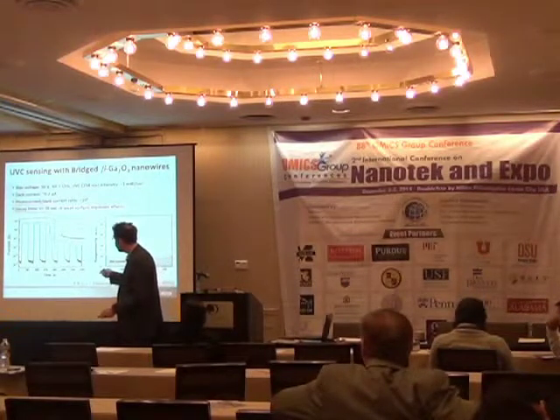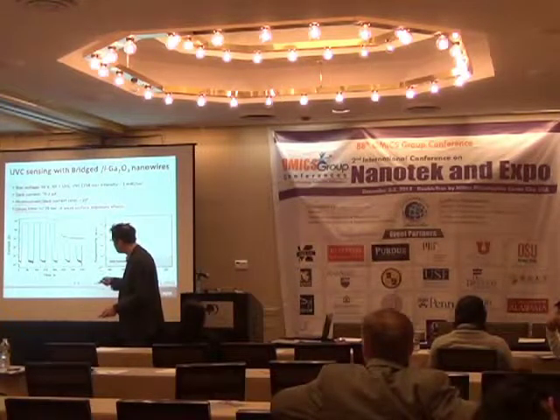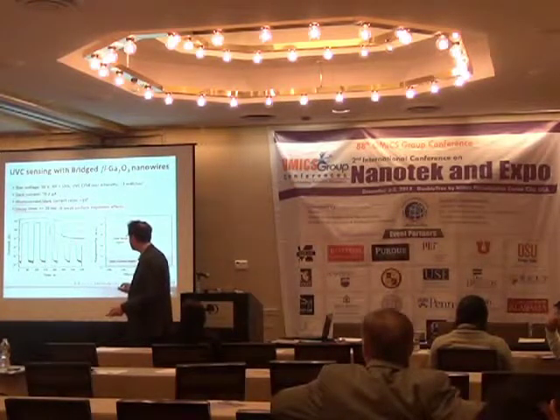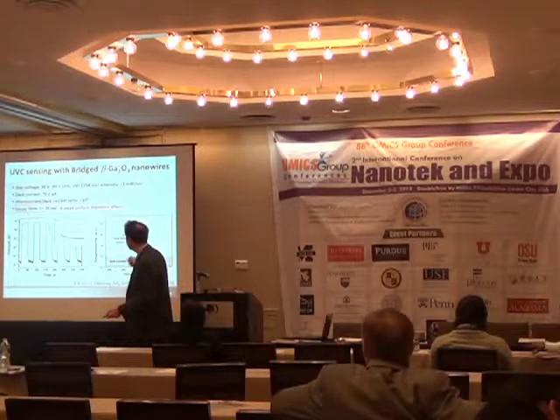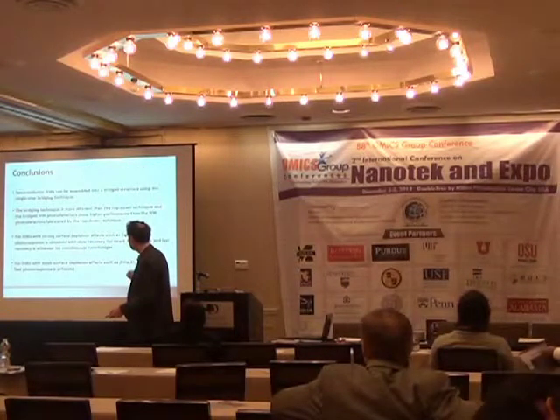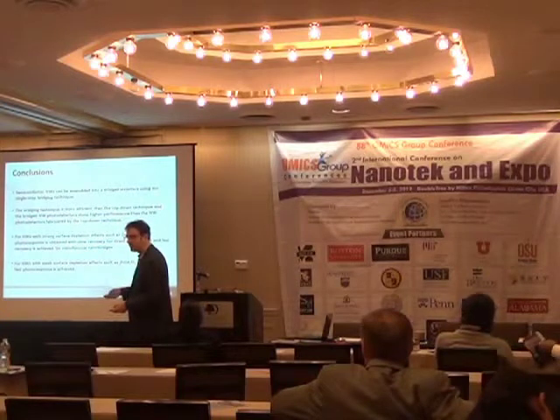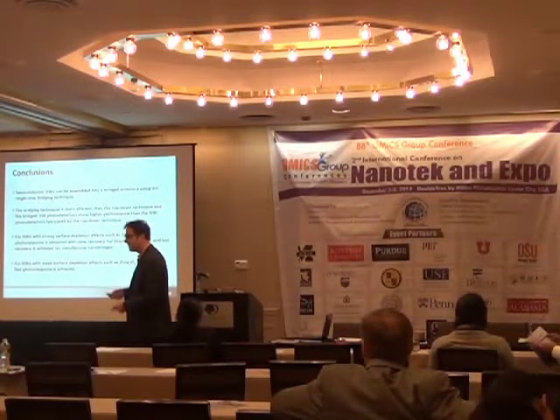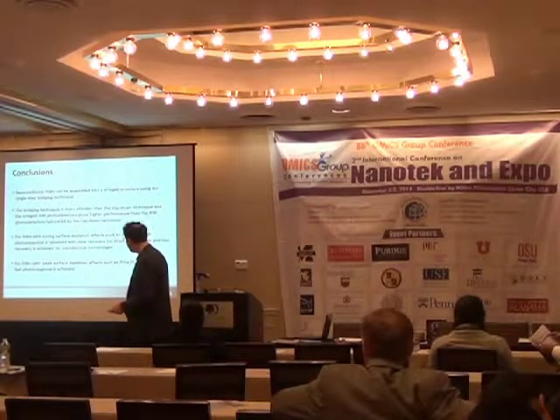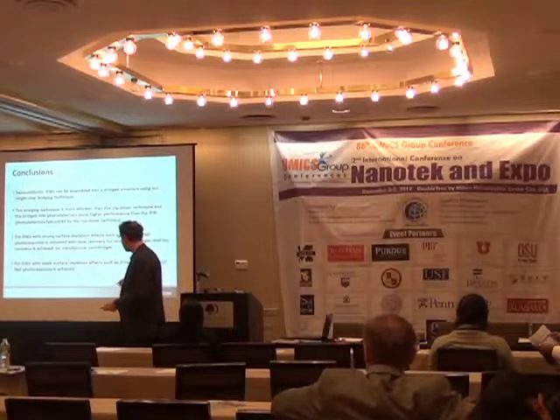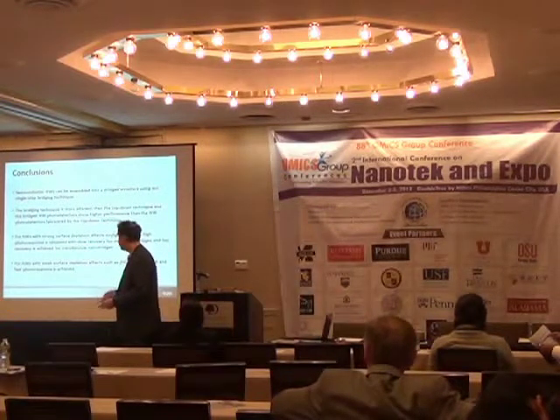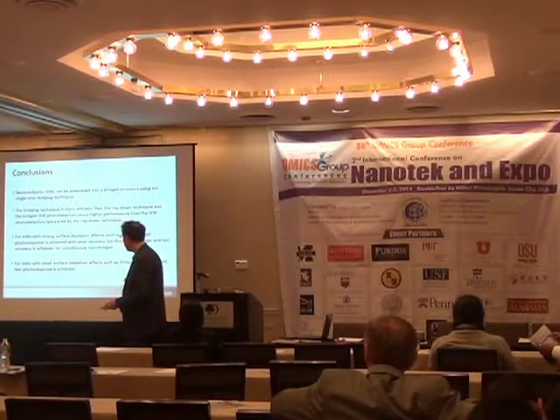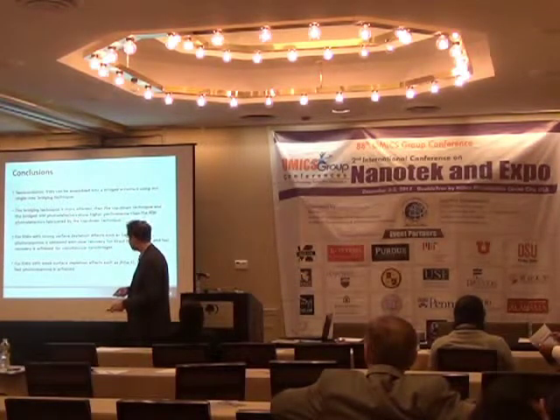Good. And this shows the response of the device, which is quite good, with a very low dark current and a very large increase in the current. So it works quite well. The response is very fast. The main difference between the two materials, as explained here: zinc oxide has a lot of defects, and therefore you have surface kinetics and a slow time response problem. For gallium oxide, you don't have this problem, so the surface reaction is not there, and it gives you a very fast response directly. Okay, good.